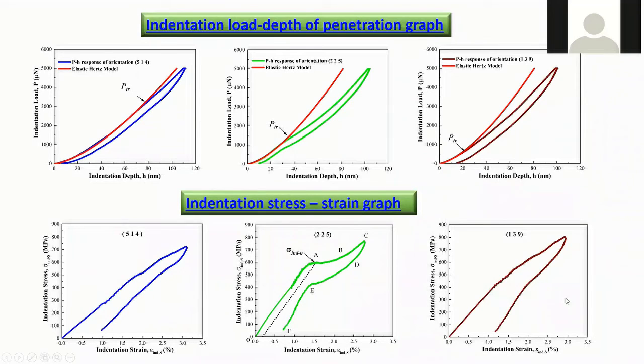So although the entire material, if you make a tensile sample out of this and we load it in tension and unload it, we see a complete pseudoelasticity, each of these grains is behaving in a completely different way. So if we want to use it for miniaturized applications, we would prefer to have a single crystal of that particular direction, which will give us the best pseudoelasticity. That was what our target was.